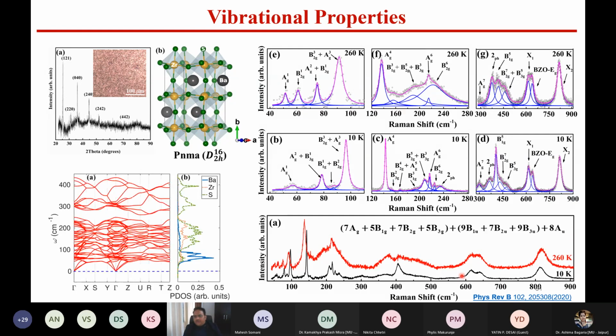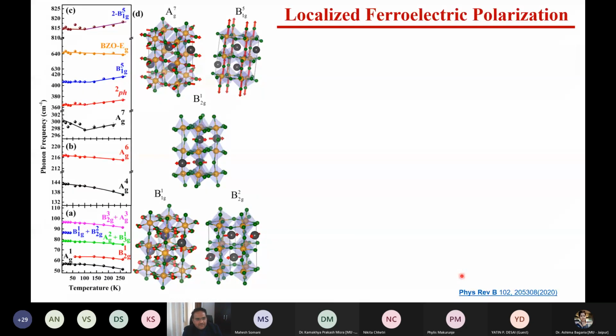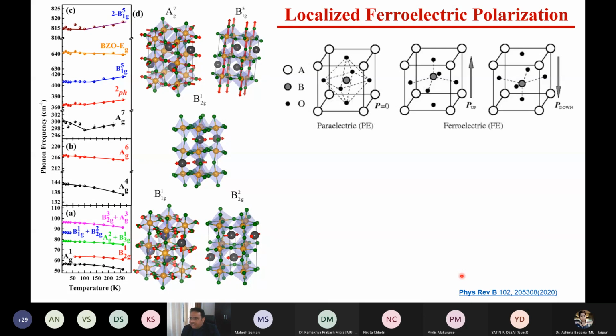So we have done low temperature Raman studies to understand what is happening in the structure which is supporting this particular material. And we try to understand the complete phonon dispersion and the phonon vibrations, the atomic vibrations, in these materials. And what we realize is that these materials are interesting because the structural distortion, especially the rotational modes, are important to create ferroelectricity in these materials.